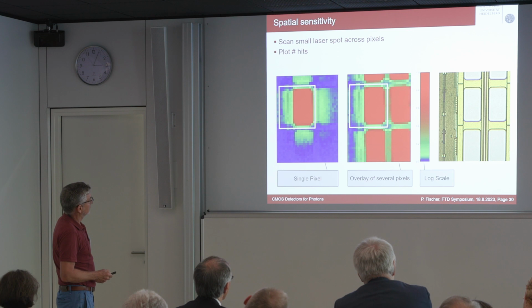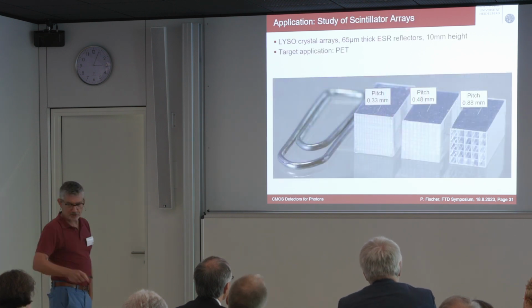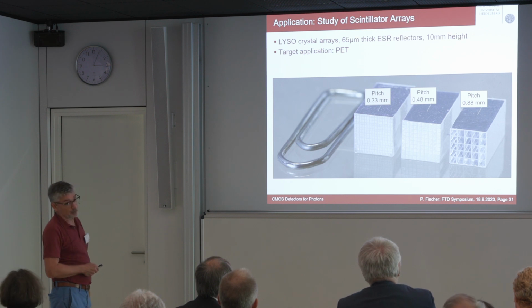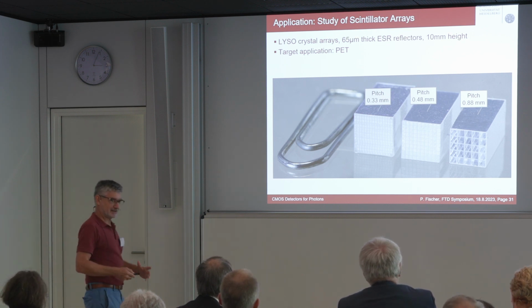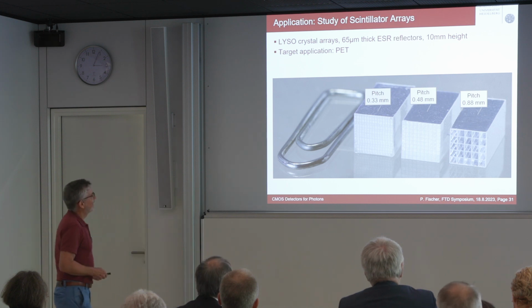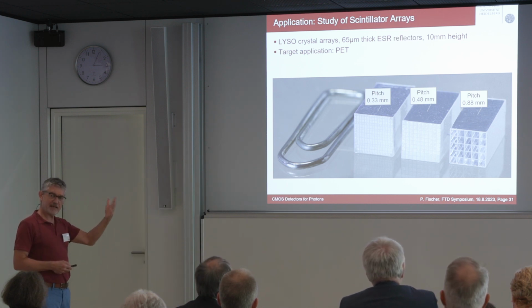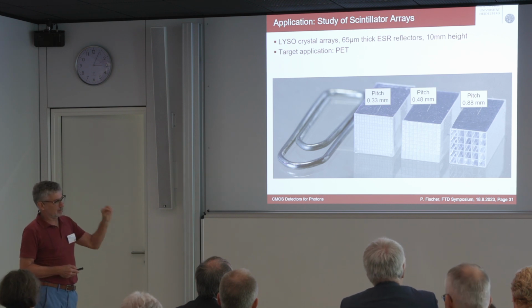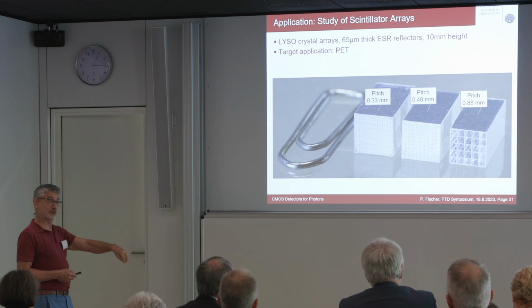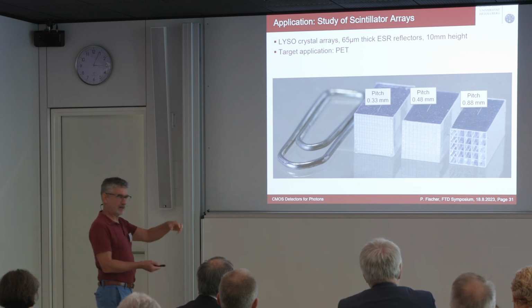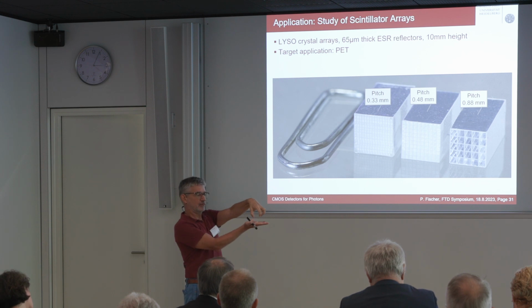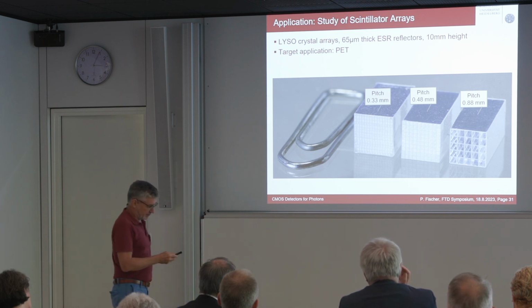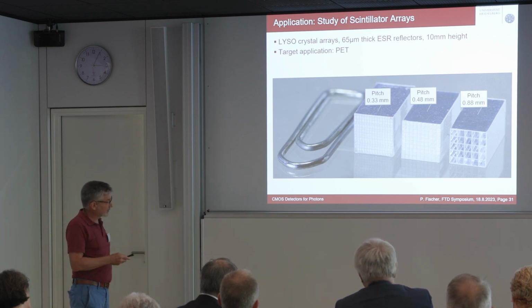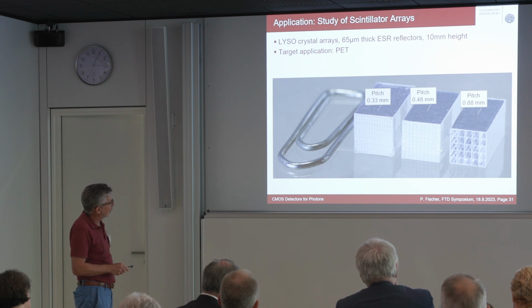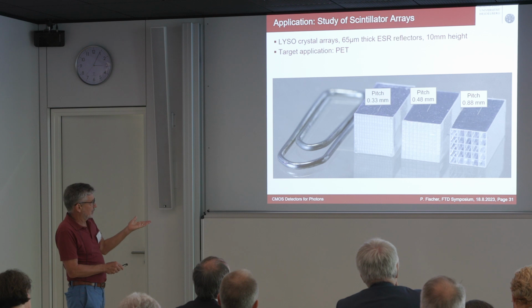And I show you one first application which you will like. We have been working on PET for a long time because these are particles, more or less, not really. And the way you detect the gammas, the high energy gammas in PET, is you absorb them in a scintillating material. They produce photons, and you look at the photons. The normal way to do it, you have the scintillator, you have one of these avalanche silicon photomultipliers underneath, and you see a click. And sometimes people try to get some position resolution by segmenting the scintillator into small needles, and then to measure the position where the light comes out.